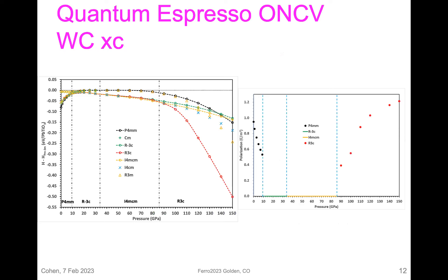I came back to this relatively recently. What we did was some really careful pseudopotential calculations, making new pseudopotentials and making sure they agreed with all-electron LAPW using the ELK code. It turned out that these are relatively small energy differences, and we finally nailed it down. I can very briefly say what I think is the right answer.